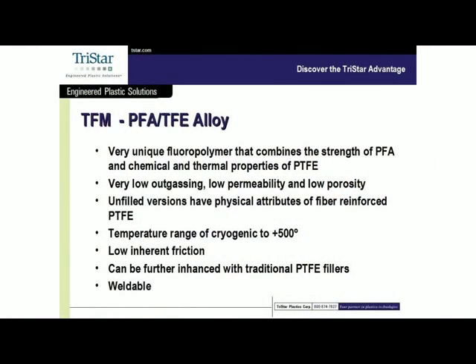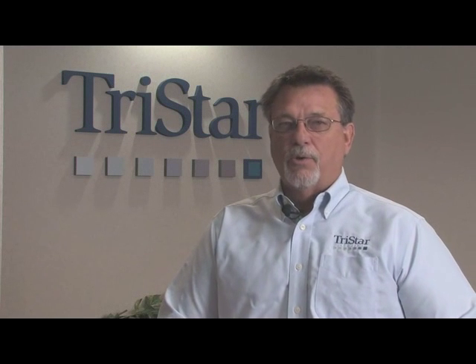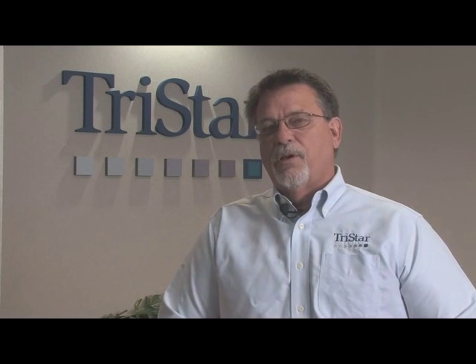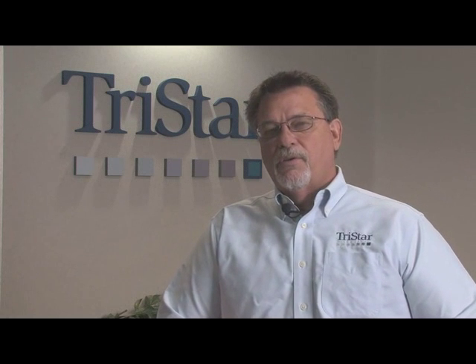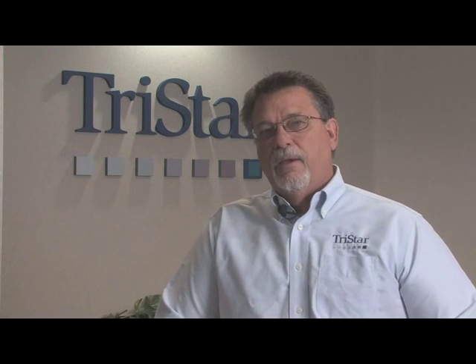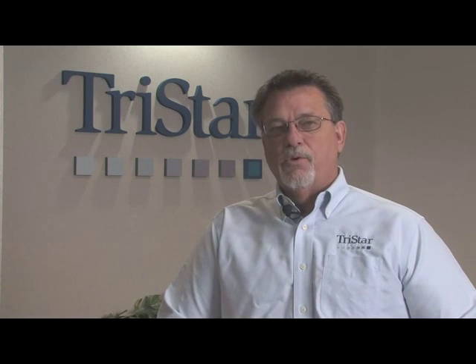Now, one thing that can be done with TFM, again, because it's got some PTFE in it, is that we can put some of those fillers in that we use with PTFE and further enhance it. So if there's applications where you're looking for, say, heat dissipation, we can add carbon fiber. If you're looking for a little bit extra lubricity, migratory lubricity, you can put graphite or moly in it. So it is diverse enough in terms of what we can do compounding-wise to give us a material that can be modified to meet specific requirements utilizing this TFM. And then I mentioned that it was weldable. This again is a material that you can use traditional PFA welding techniques and weld other fluoropolymers using the TFM.